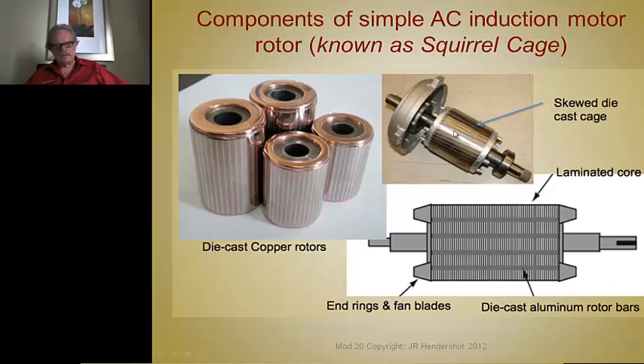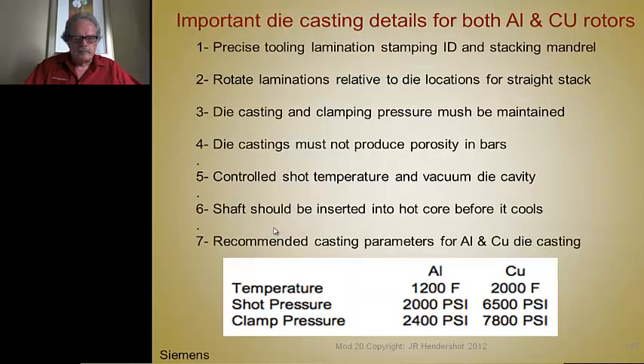You can see the beautiful stacking here, skewed stack, and a beautiful casting job here, been machined. And here's the fan blades, and here's an example of some die-cast copper rotors with quite wide slot openings, and the copper's cast right to the surface of the OD, which is a good thing. You want the bar conductors as close to the OD as possible for an inverter-driven motor to reduce the leakage reactance in the rotor. And this keeps the power factor up, so that's a good thing. So that's a beautiful example.